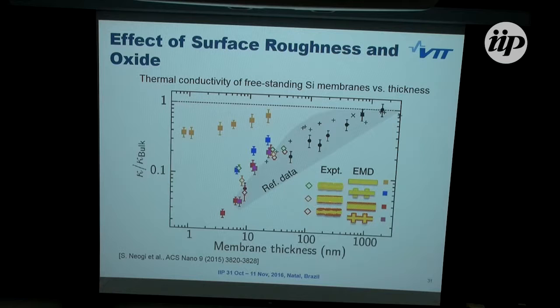And then this is a thin oxide. And then, let's say after a shelf life of a few weeks or something, it's a fully grown native oxide on top of the sample. And actually, the thermal conductivity goes down by a factor of 20 or something, so it's quite good. And it has a very strong effect, of course, or potential for the thermoelectric application of silicon, as I'll show you later.